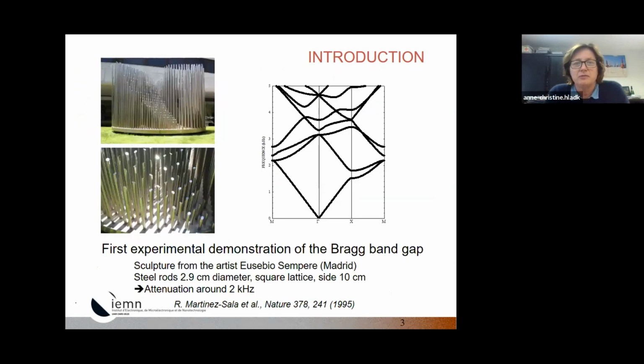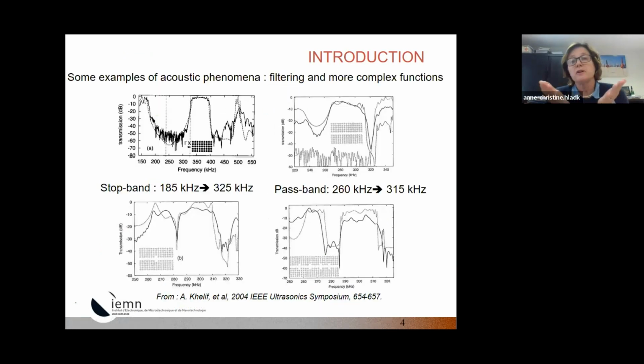So here, rapidly, the first experimental demonstration of the Bragg band gap. It is with a sculpture from the artist Eusebio Sempere in Madrid. You have steel rods, 2.9 centimeter in diameter, square lattice, side 10 centimeter, and you have an attenuation around 2 kilohertz. And if you draw the dispersion curve here, you see that you have a band gap in a particular propagation direction. So filtering is the main application, the first application of band gap, but you can imagine more complex functions using the band gap.